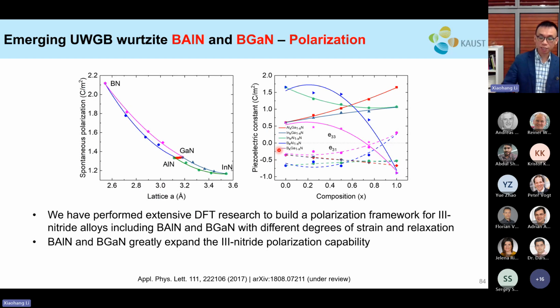And in addition, this group of materials has some very interesting characteristics. For example, if you look to the right, especially the blue and the purple solid and dashed lines, you can notice that at a certain composition the piezoelectric constant of the purple line, sorry, maybe it's pink, pink and purple, and the blue line, they will cross zero at almost the same time. This has not happened before for other nitride materials because their piezoelectric constant remains either positive or negative across the composition. But this crossing at zero for BAlN and BGaN is very, very unique.